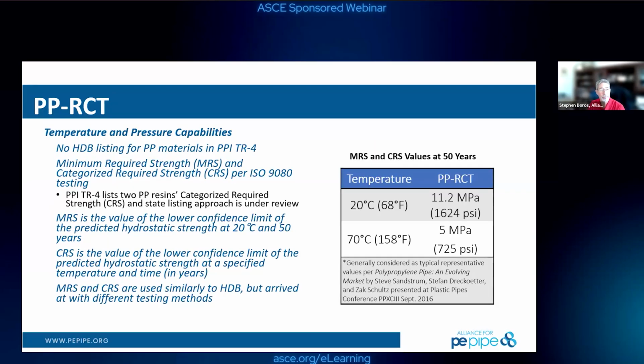So on the PPRCT side, it's not just the material. The materials do have PPI ratings, and then they have what's called MRS under the ISO system for long-term strength rating of their materials. So there are materials listed by PPI, just as there are for polyethylenes and every other type of thermoplastic. The MRS is typically at 20 degrees C, then you have to determine what's called a categorized required strength when you go up to higher temperatures. So you can see these are all long-term stress rated materials to make sure you have that long life in the application.